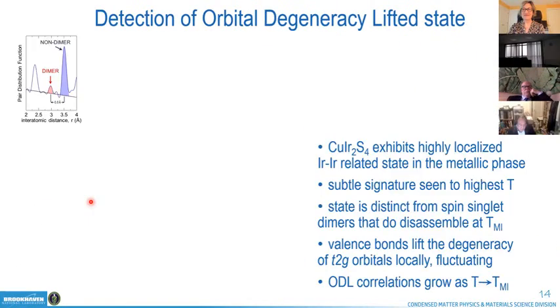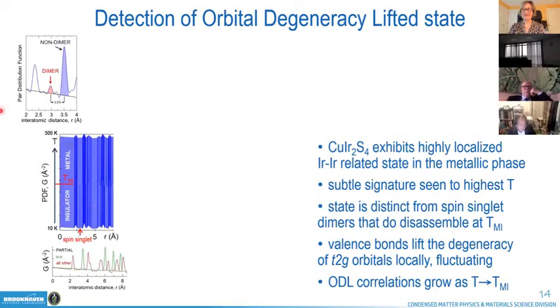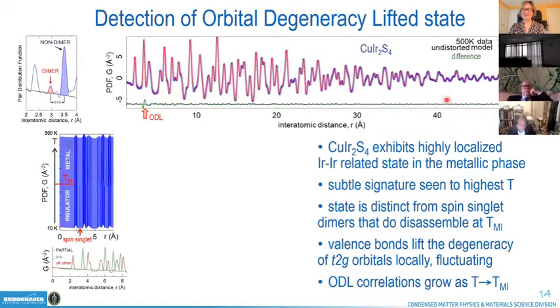Fine. So what we have done next is we went deep into the high temperature regime and fitted a nominal cubic model to this data. And what you observe is that the fit is spectacular all the way, except underneath this peak that corresponds to iridium, which shows this very delicate signature. This signature survives to the highest temperature measured. In this case, it's around 500 Kelvin. We could not go higher because the system presumably decomposes.